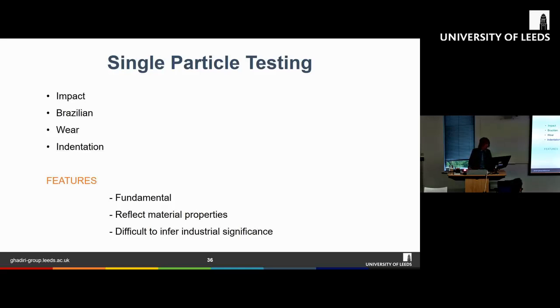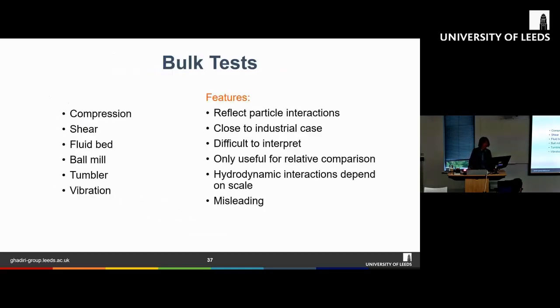Here are some examples of single particle testing that can be done. For example, impact test, Brazilian test, and indentation test. The features of single particle testing are that they are fundamental, and they reflect the material properties of single particles. But the problem with single particle tests is that it's very difficult to relate them to industrial application. Therefore, in industry, most people will prefer using a bulk test.